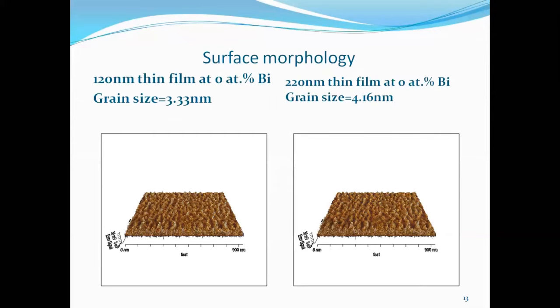Then the next slide, I've used the same bismuth concentration, 0 atomic percent, and I've changed the thickness. The first one, to the left, is the 120 nanometer thin film. The second one is the 220 nanometer thin film. Both of them at zero atomic percent bismuth. But you can see now with the change in the thickness, the thinner 120 nanometer film has a 3.33 nanometer grain size, while the 220 nanometer one has a 4.16 nanometer grain size.